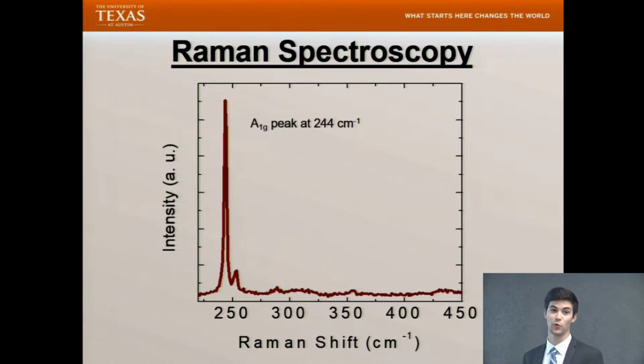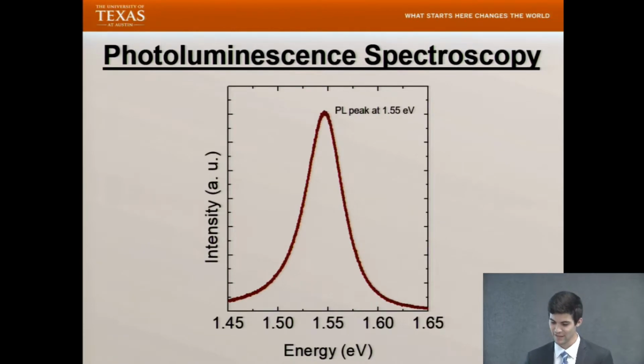Next, I performed Raman spectroscopy on the potential monolayers. So if the Raman peaks were consistent with published reports in the literature, then I was able to determine whether the material I grew was actually molybdenum diselenide or something else. The final step of characterization was photoluminescence spectroscopy. And by comparing this peak to the literature, I was able to determine the thickness of my domains. So that way I could confirm whether or not my domains were monolayers.